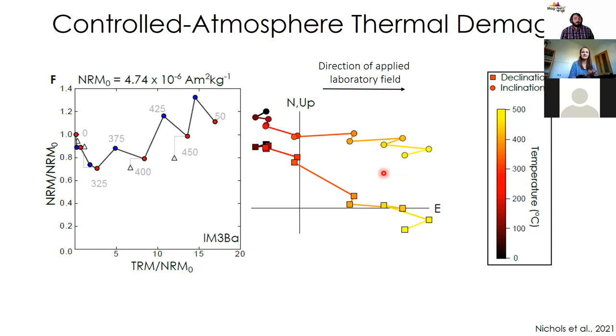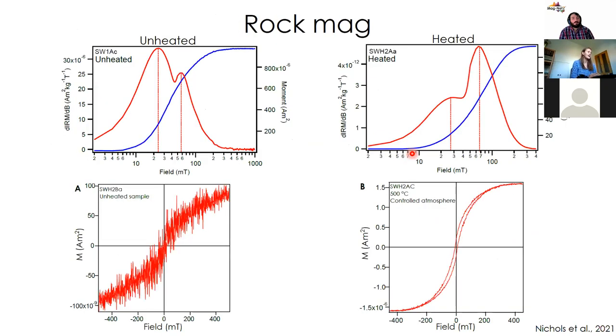So then we tried more standard techniques. We did some Thellier experiments in a controlled atmosphere, in a standard paleomagnetic oven with a CO2 H2 atmosphere to control the fugacity. And as you can see, this is our Arai diagram. They alter spectacularly. Our pTRM checks, these triangles, sit miles away from these points here, and it's trending in the wrong direction. And if you look at the Zijderveld, the points are romping off in the direction of the applied laboratory field. So this is very clearly altering, even though we're measuring it in a very reduced atmosphere. And actually, that was probably the problem, the fact that our atmosphere was so reducing.